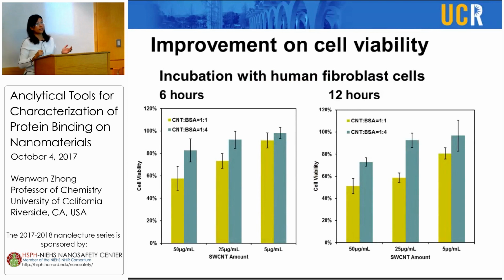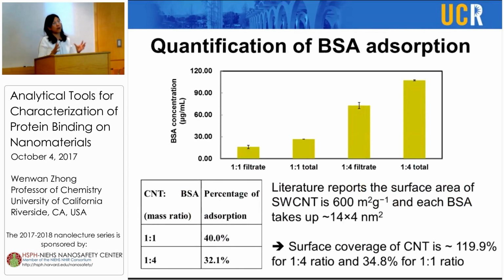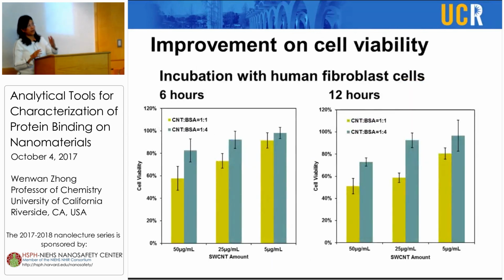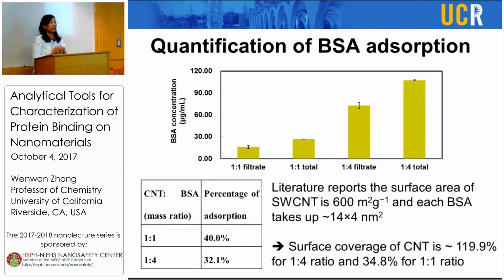toxicity. So when we incubate this with the fibroblast cells, we see that coating with more BSA enhances the viability of the cells compared to the non-coated. Larger coating, more coating of BSA increases the viability, because we cannot distribute the bare carbon nanotube into serum. So that's why we did not include it in here. And then also we quantify how much the surface coverage is, right? So we can observe it in AFM, seeing the carbon nanotube growing thicker.